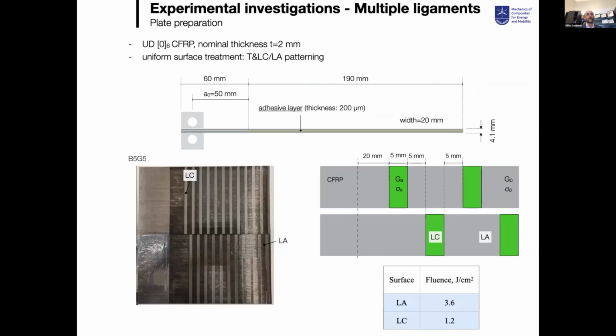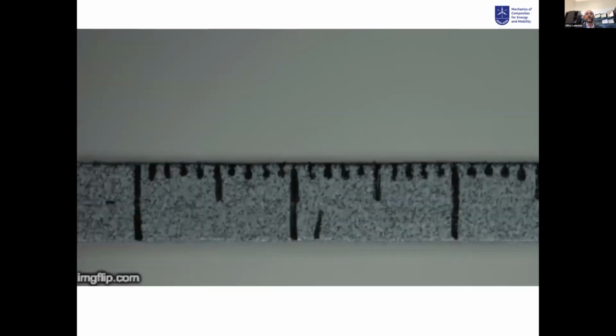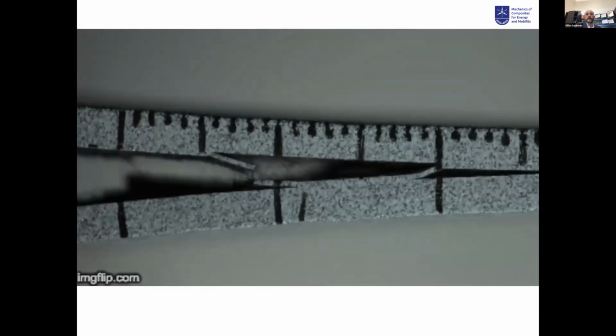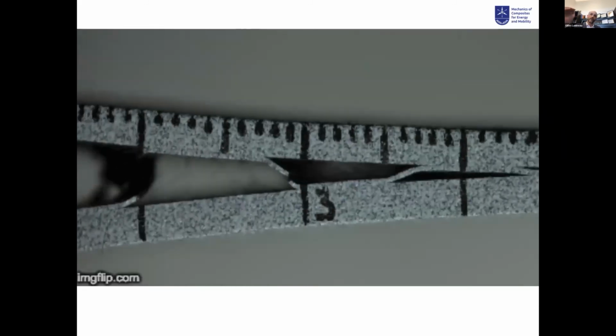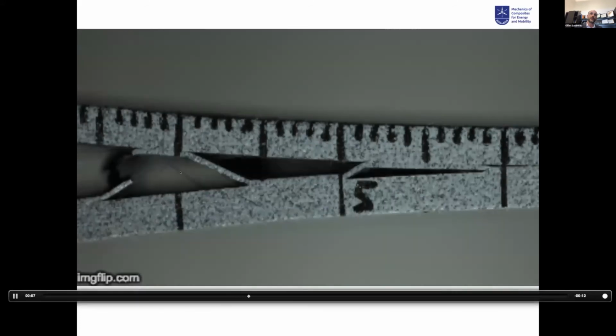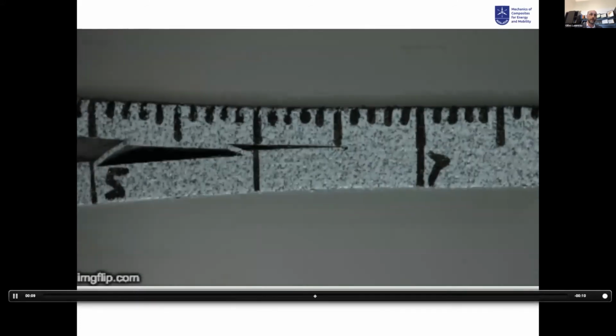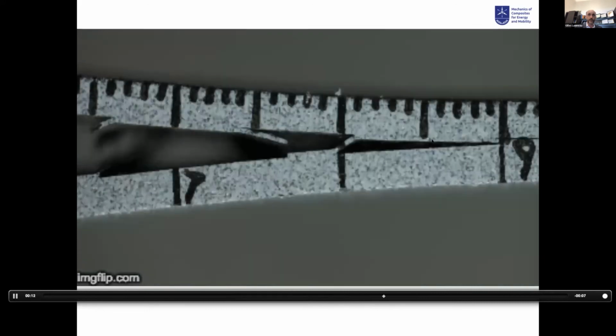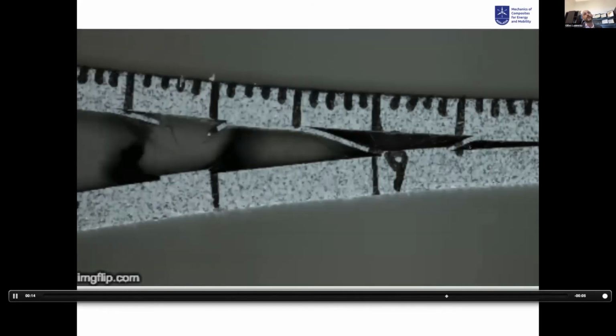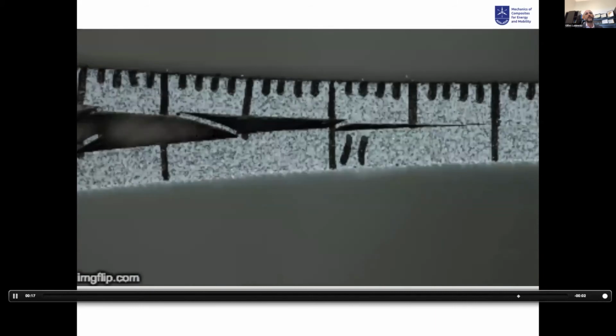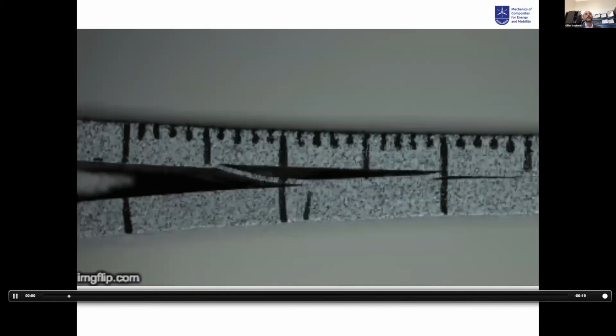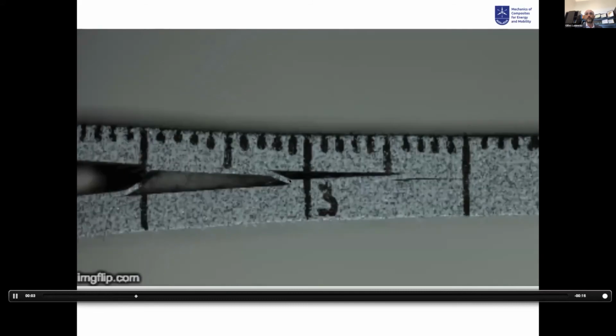So here now you are taking two composite plates, you make a kind of pattern laser treatment like this. So you recognize here the different pattern that I was showing before with alternative properties of strong and weak, strong and weak, strong and weak. And what you see during the delamination now is something like this. Instead of a very simple macro-crack of DCB delamination, you start to see the creation of a family of ligament bridging like this. And this is something that you control by design. And this is really beautiful because you have plenty of dissipative events of your bond line just by modifying the surface treatment that you put on your composite before.